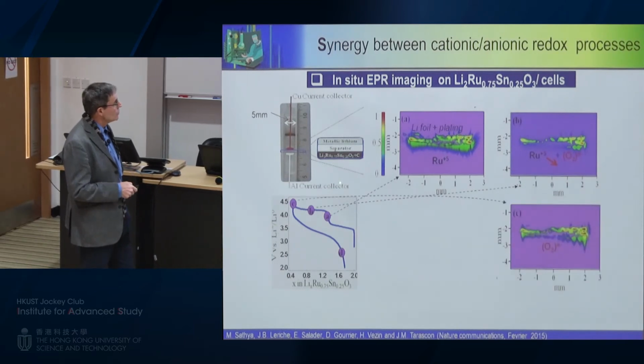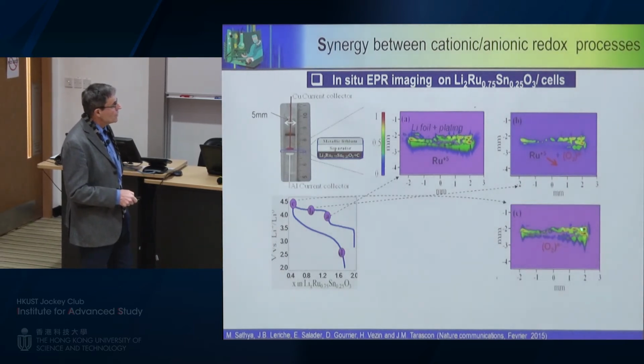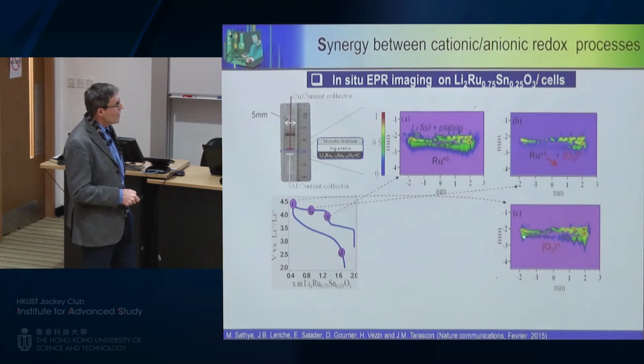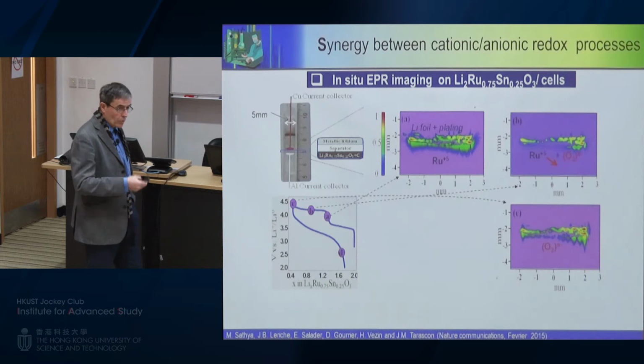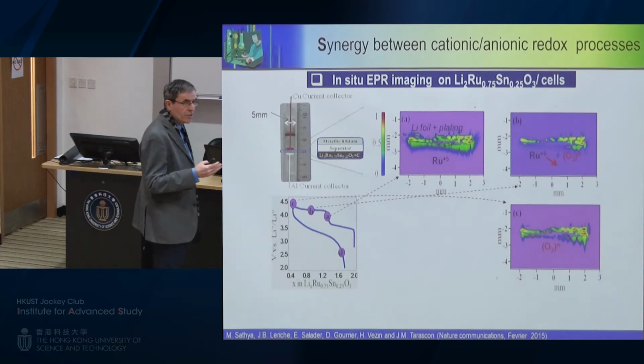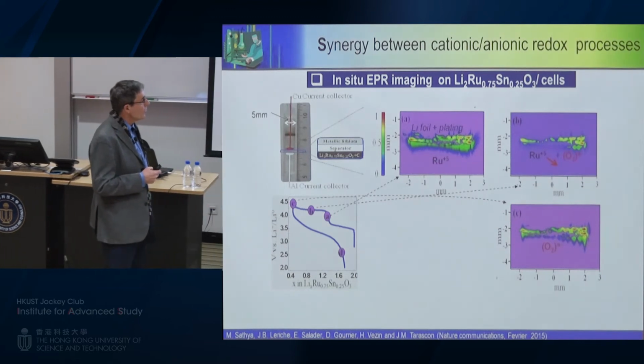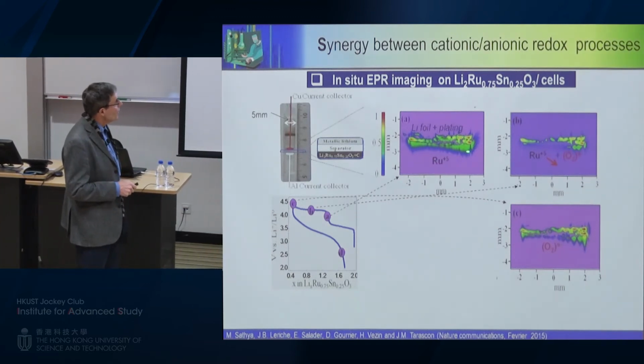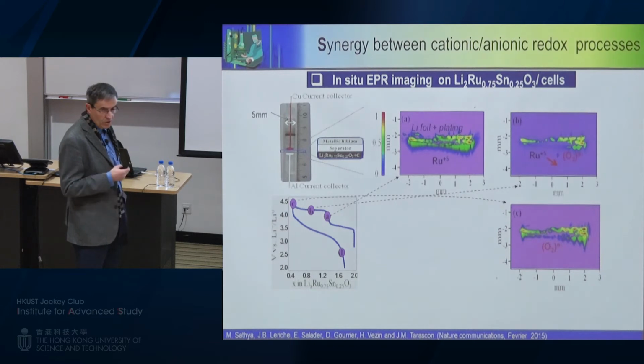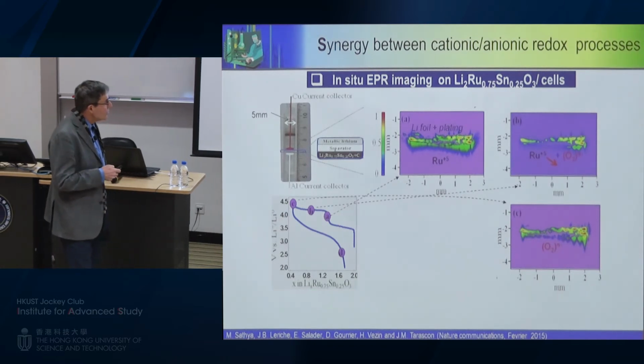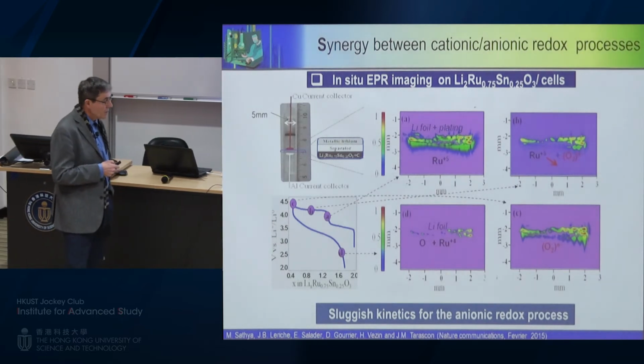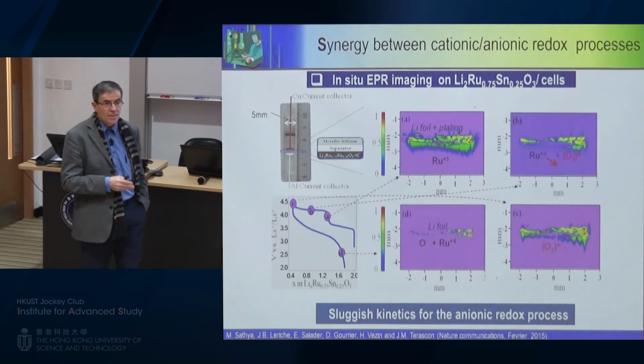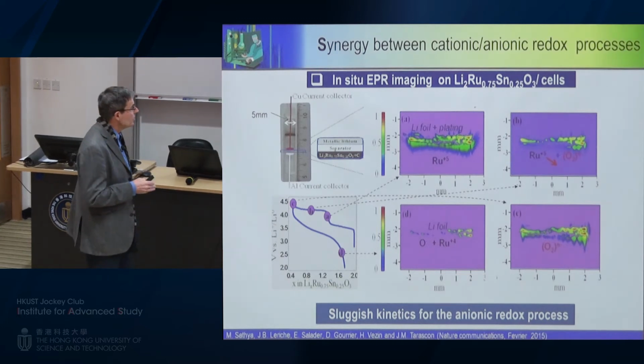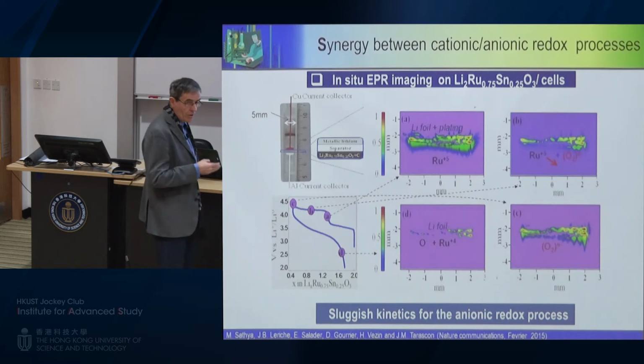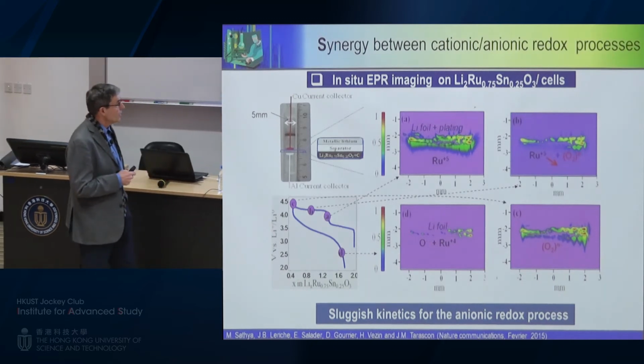If I follow up the charge to the complete charge, you can see again some more accumulation of lithium at the negative electrode. But now, look, the positive electrode becomes greener because you have now more spin associated directly to this oxygen peroxo species. But what is very interesting, if you compare the two images, you can see here that I have homogeneity of the spin, while here, it is inhomogeneous. And this is going to give you a very important information, which means, and we will come back to this issue, that the kinetics associated to this anionic redox species are very sluggish. And this will have a great importance.